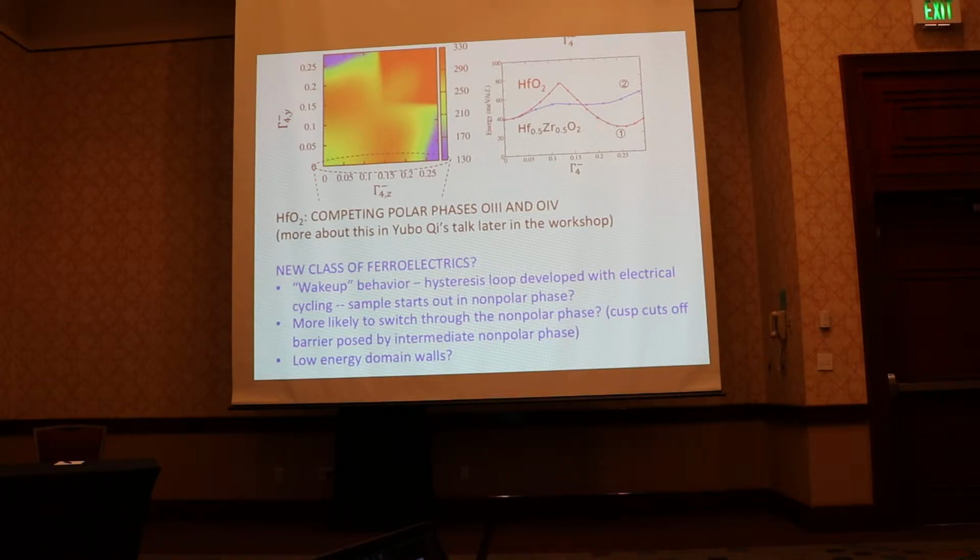But looking at this energy surface as a function of the polar mode, I'm going to throw out the idea that we should consider this a new class of ferroelectrics, because we have here a polar mode, but instead of continuing this curve up to a high energy at the nonpolar state, it takes a sharp turn and goes back down. So in these materials, we see things like wake up behavior, where after the material is first synthesized, you develop the hysteresis loop with cycling, so you're starting out with part of the sample here, and then eventually driving it by cycling into the polar phase.